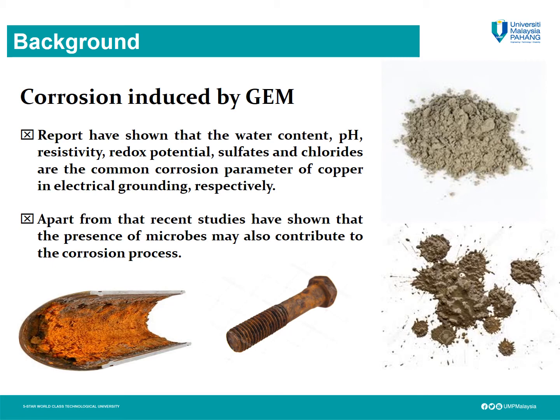Reports have shown that the water content, pH, resistivity, redox potential, sulfates, and chlorides are the most common corrosion parameters of copper in electrical grounding. Apart from that, recent studies have shown that the presence of microbes may also contribute to the corrosion process.